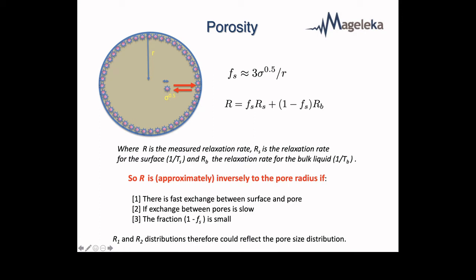Well, of course, the surface area inside the pore, we can directly relate that to a radius. So that means that we can get the radius of a pore directly from the relaxation time. And in a complicated system with complicated shaped pores, channels, connected pores, disconnected pores, we can dig into the internal structure a little bit as mercury porosimetry does, but with a much simpler and a much safer experiment.